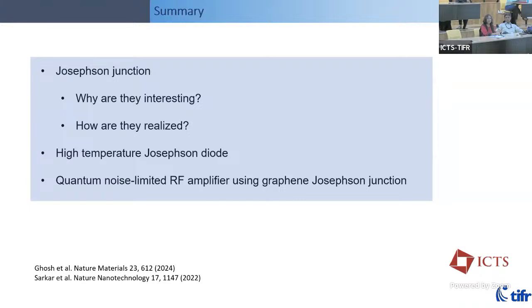So of course, BSCCO is known for its very good cleavability, and did you use single layer BSCCO? No, for none of these experiments that I talked about do we use single layer or single unit cell BSCCO. A unit cell is about 3 nanometers thick. We use about 10 nanometers. We work very fast to reduce the degradation, but the degradation is happening, because even if you do it in a glove box, you have to put it in a cryostat.